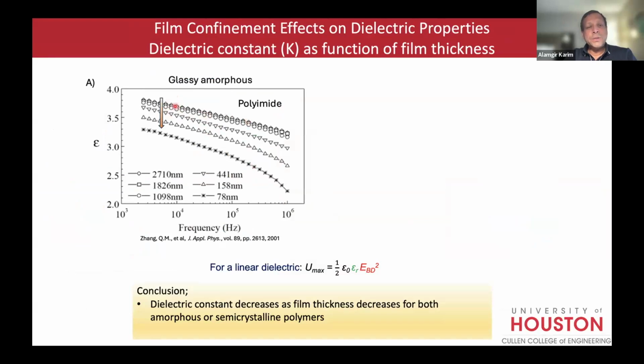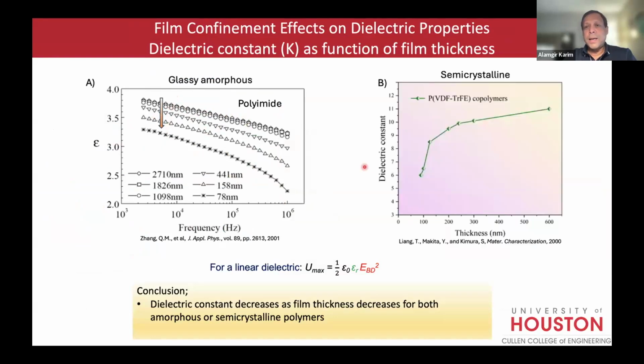So you see, as you decrease film thickness, the dielectric constant goes down for a glassy amorphous polyimide material, for instance. Also for semicrystalline PVDF. As you can see, as you reduce thickness, nobody's really looked at these in great detail in the submicron regime. People have shown it for 100 micron down to 10 micron. Actually, energy storage goes up. I'll show you, but not in the submicron regime, which is where we want to make them really ultra thin.